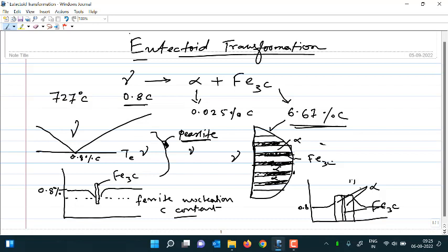And depending on whether cementite or ferrite is forming, it could be either consuming carbon or it will reject carbon. Okay. If it consumes carbon, then you know that the carbon content is going to decrease around that lamellae, right. So, that will create a condition for the nucleation of the ferrite phase, because it has lower carbon content. Similarly, the other way around, if ferrite forms, the carbon content around the growing ferrite lamellae would increase, because it has to reject all the excess carbon that it cannot accommodate. So, that will create a condition just adjacent to it for the growth of a cementite lamellae.